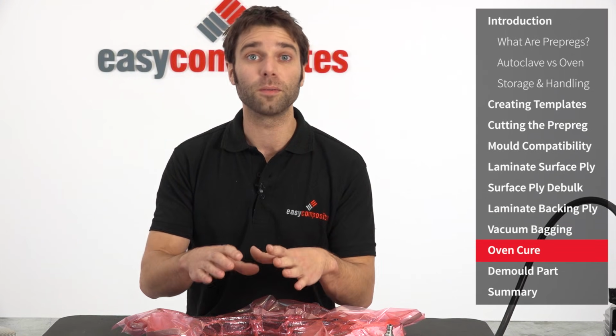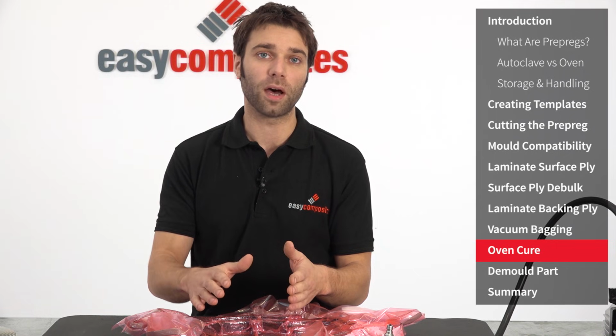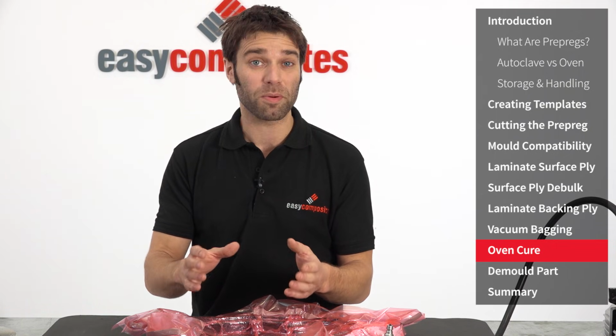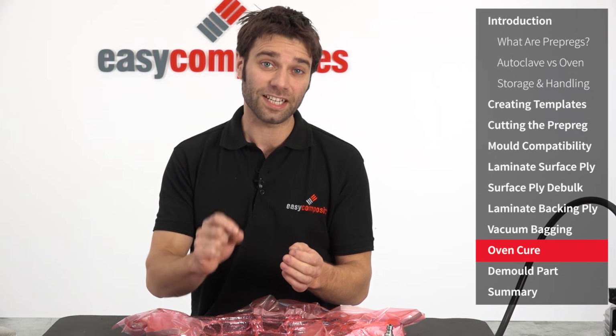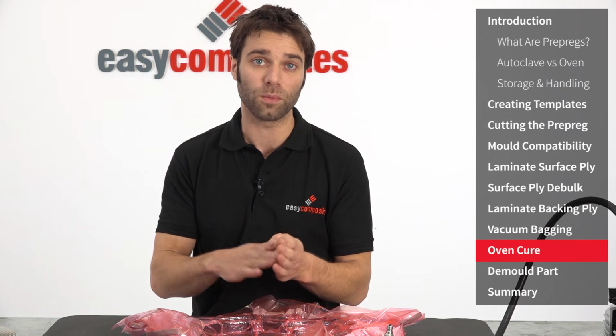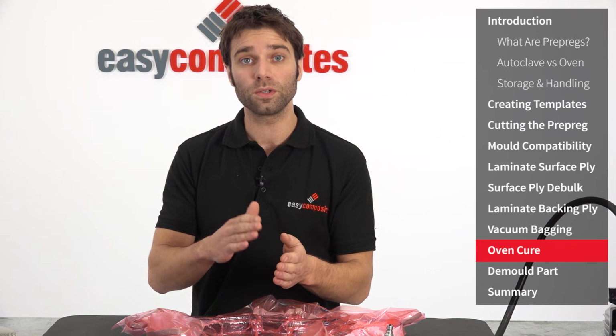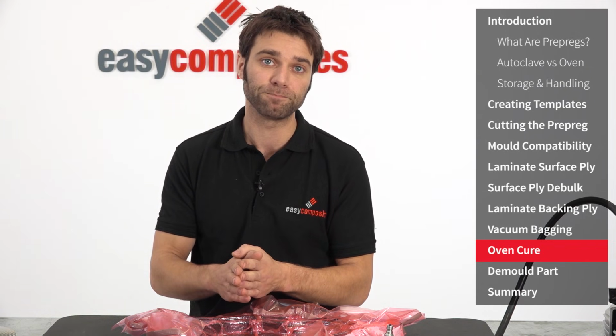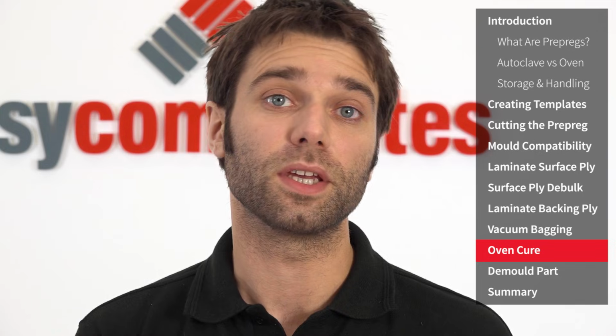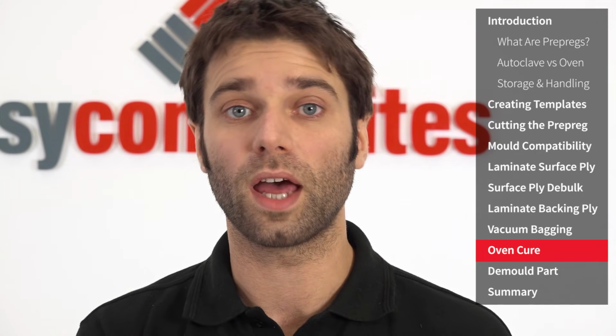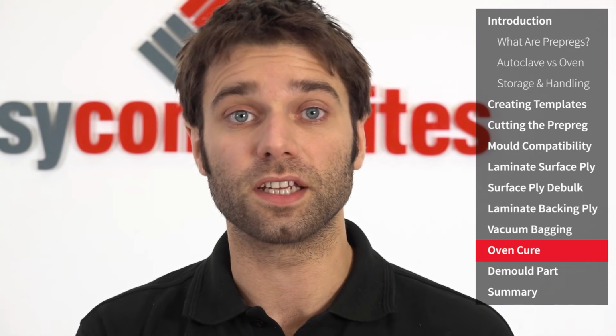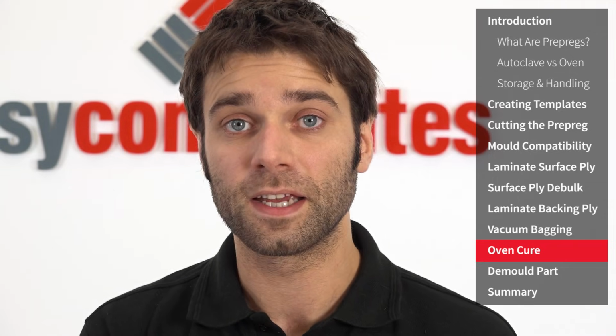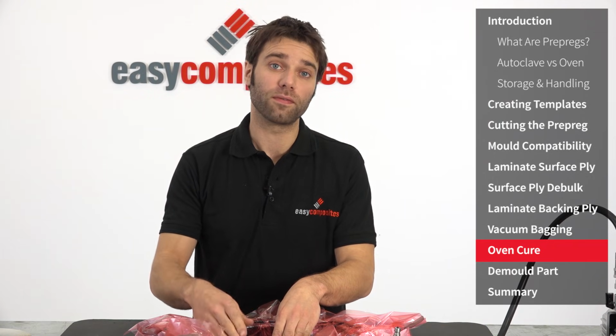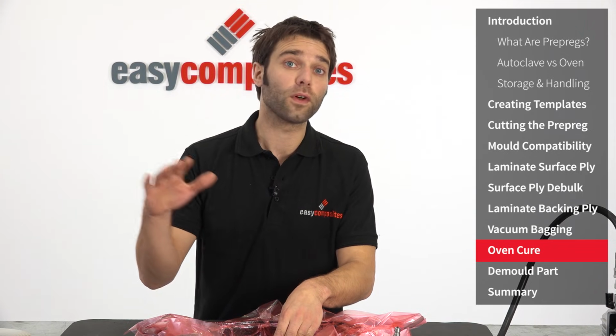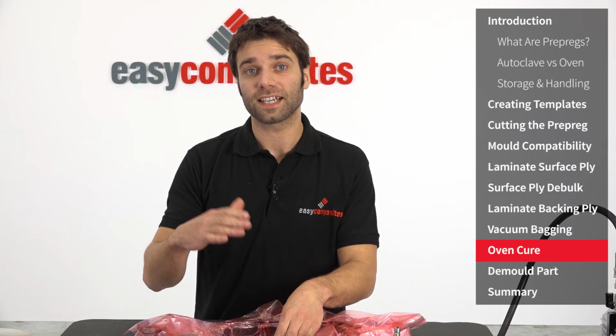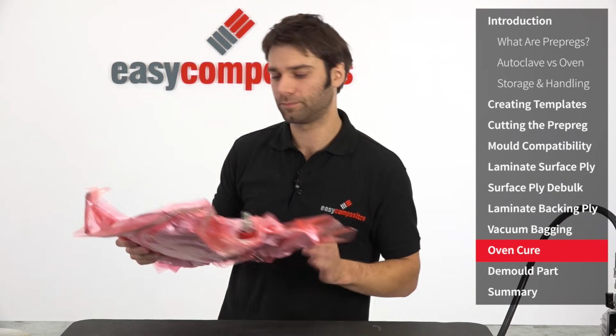With this component now vacuum bagged properly, all that's left to do is to cure the part. To get the incredible results that this prepreg system is capable of, it's absolutely essential that you follow exactly one of the XC110 cure cycles, which use a two-step cure to ensure optimal flow of the resin. There are some alternative cure cycles that can be used depending on your oven control and mould material, so please check the datasheet to find the cure cycle that best suits your needs. Because this mould is made using the XT135 tooling prepreg and our oven has full ramp and soak control, we'll be using the XC110's standard cure cycle.